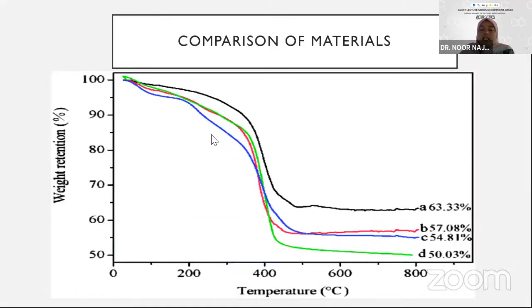Okay, and we can also compare between the samples that you have produced with different types of fillers, or different percentages of fillers. So you will get different percentages of residues. You can analyze the effect of adding this kind of filler, so the decomposition temperature is higher compared to the sample without any fillers. That is how you analyze the data.